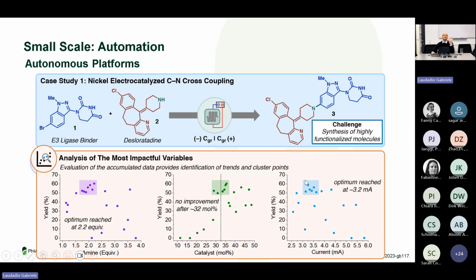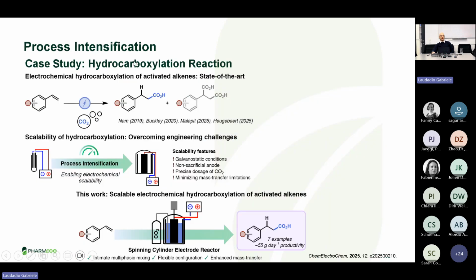Okay, so this is pretty much a story about very small scale. Now let's assume that we have our reaction and that we want to scale it up to, I don't know, decagram scale. How can we do it? In our lab, we have recently developed a system for hydrocarboxylation reactions using CO2, where basically we have used a spinning cylinder electrode reactor, where one of the electrodes is rotating and acting as a stirring element in the system to generate these hydrocinnamic acids, which may have applications in the fine chemical and also the agrochemical space.